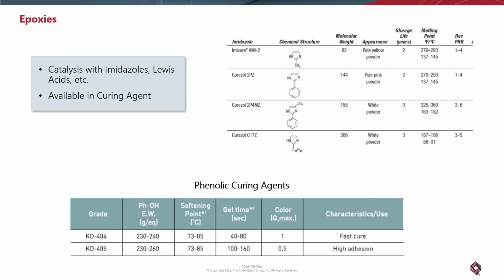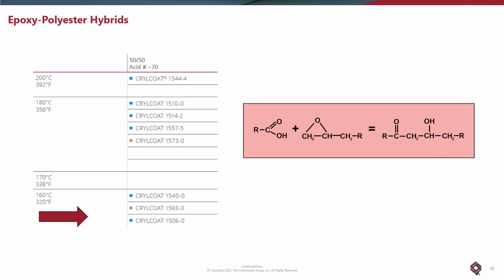You can also get curing agents that are pre-made, that are pre-catalyzed. An example here, some phenolic curing agents where the KD404 is fast cure. The supplier of these curing agents is just putting in a dose of imidazole catalyst to make it cure faster and at a lower temperature.